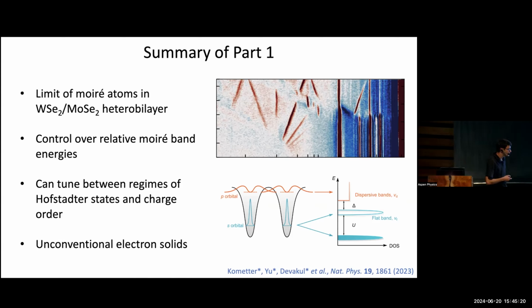That's right. So for this particular sample, it's a heterobilayer. All we could do as we were assembling this was look at the crystallographic axes of the flakes as we were picking up. These things tend to be in strips, and so you can usually see some crystallographic axis. You don't know if it's a zigzag edge or an armchair edge, so you don't know which stacking you get for the heterobilayer before you stack it, but you try to come close to aligning these edges so that the twist angle is low, because it's at this low twist angle where the Moiré superlattice dominates. So the 1.33 degrees or something, that order of magnitude for this particular sample was a fluke, but it's nice that it was in this low twist angle regime.